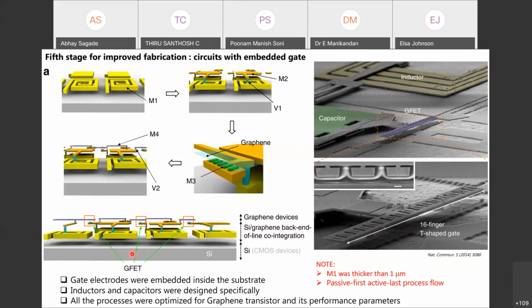So when you are looking at this silicon substrate, these are the gate electrodes. These are embedded below, inside the substrate. And that's why it reduces the noise and improves the signal. That process flow technology, they called passive first and active last. Passive first means all these LCR components are passive components, so you fabricate those first because they require high temperature, above 400 degrees centigrade. And at the end, you fabricate the active component, like a graphene transistor.